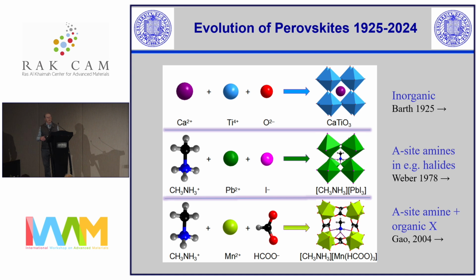And the perovskite world has evolved over the last 100 years, from the first inorganic perovskite, which was characterized in 1925. In 1978, there was an important paper where a group in Stuttgart with Weber and co-workers made the first hybrid perovskites, where they put an organic amine cation into the cavity of a lead halide perovskite. And so one of the materials they made was actually the methylammonium lead iodide that everybody talks about. And it was another 30 years before people realized that that was actually a really interesting compound that spawned a massive amount of work. At the time, they were making it just for curiosity and so on. So there's a good lesson there.